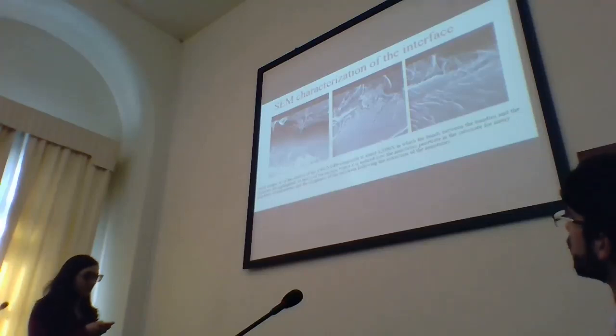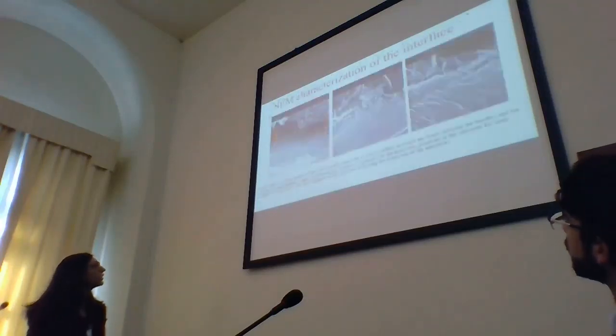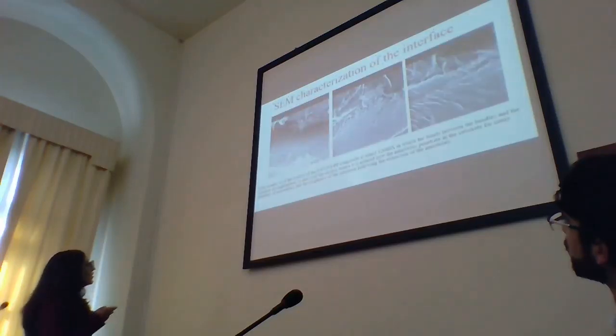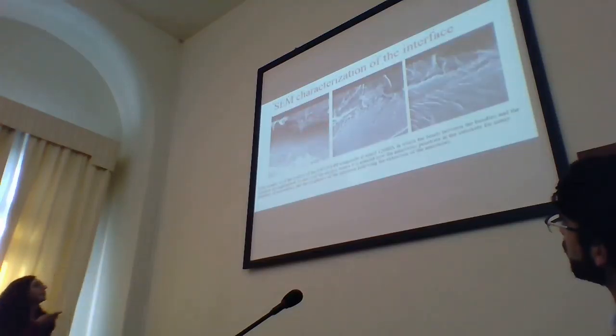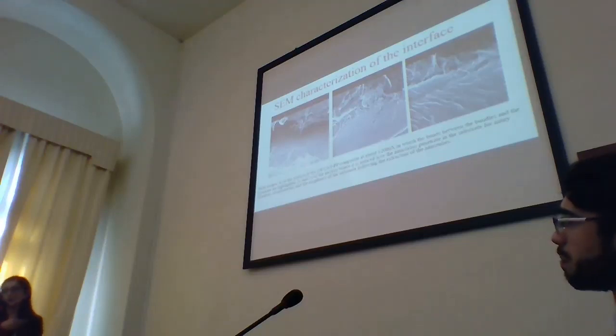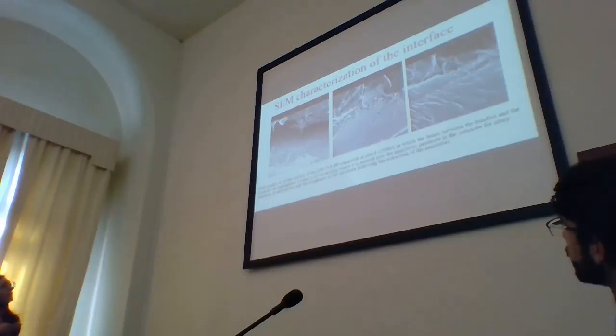In particular, in the first image, we can see that the layer of carbon nanotubes is linked to the substrate by these roots that are linked not only to the substrate, but to the carbon nanotubes that are covered by the polymeric chain.